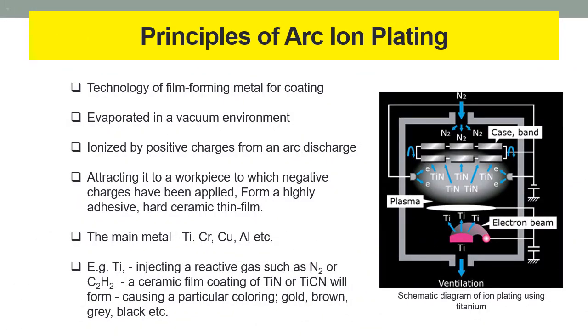Principles of ion plating. Let's take a look at arc ion plating. Arc ion plating is a technology whereby film-forming metal for coating is evaporated in a vacuum environment, and ionized by positive charges from an arc discharge, attracting it to a workpiece to which negative charges have been applied, thereby forming a highly adhesive, hard ceramic thin film. The main metal for film deposition is titanium. Chromium, copper, aluminum etc. are also used.